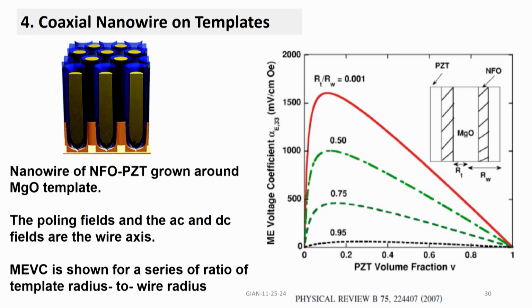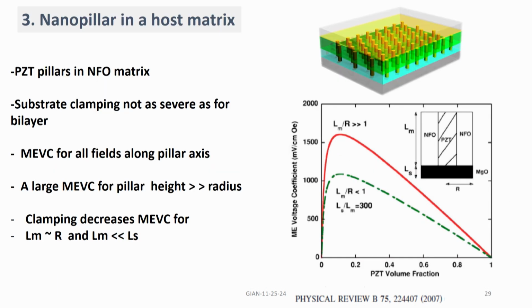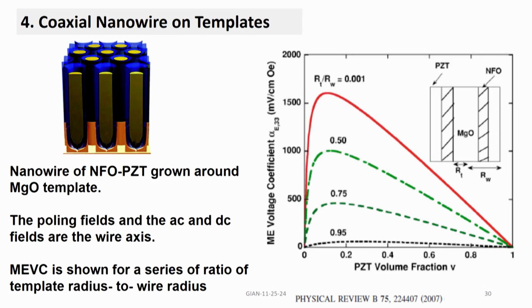Once again, when there is practically no template, there is very weak clamping effect. So, as the template grows in radius or in volume, there is clamping effect. So, there is a decrease in the voltage coefficient, and the two cases here, the previous ones, nanopillar in a host matrix or a coaxial nanowire on a template, they are approximately same magnitude for the voltage coefficient.